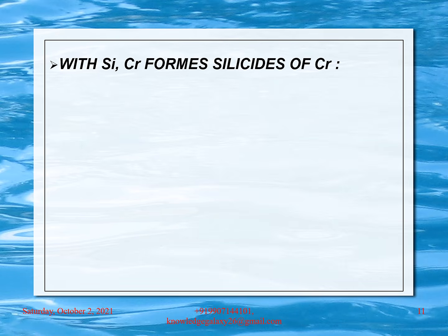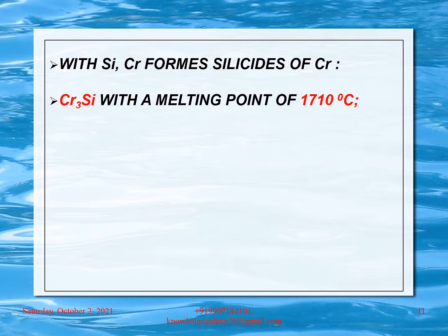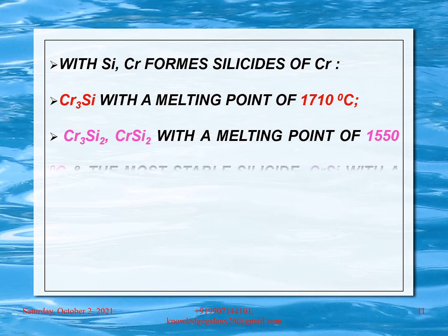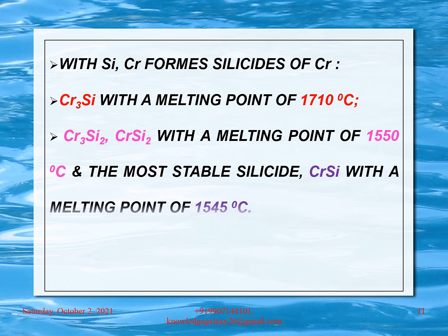With silicon, chromium forms silicides of chromium: Cr3Si with a melting point of 1710 degrees Celsius, Cr3Si2 and CrSi2 with a melting point of 1550 degrees Celsius, and the most stable silicide CrSi with a melting point of 1545 degrees Celsius.